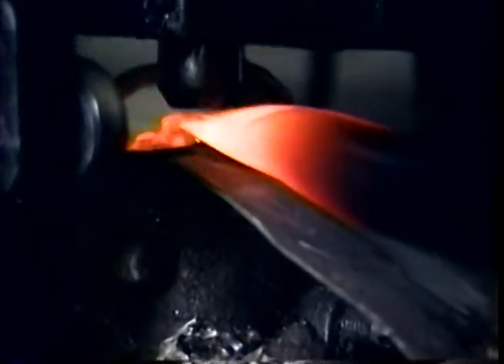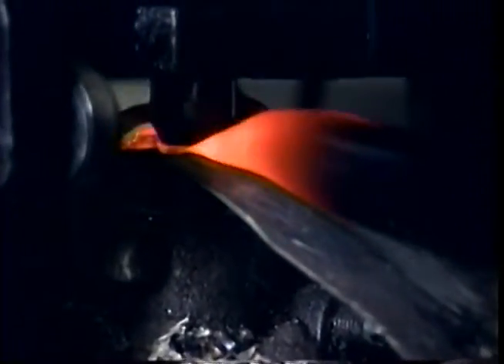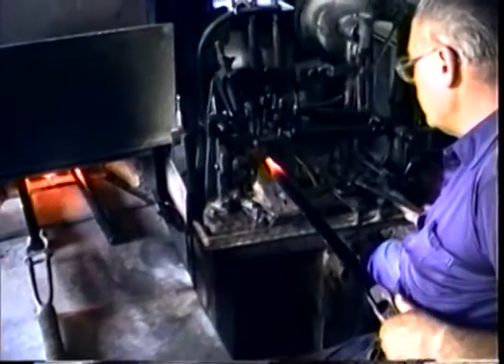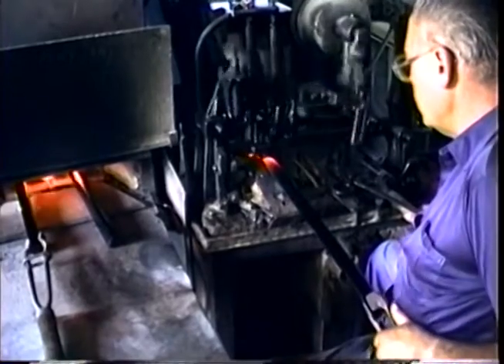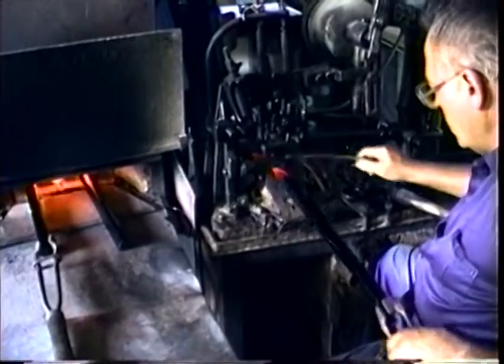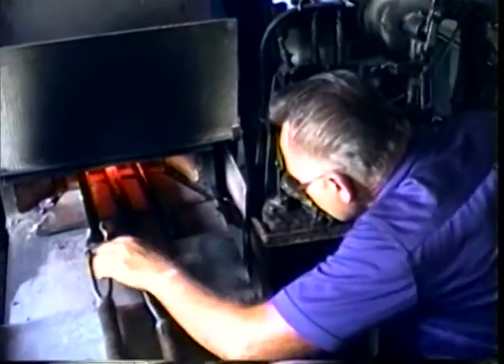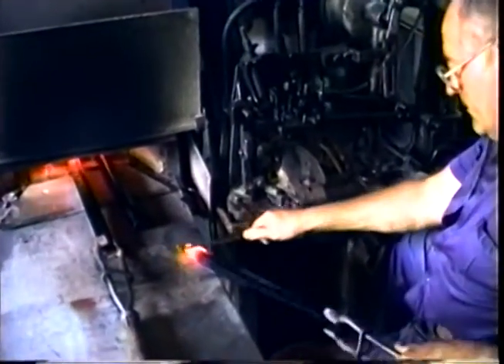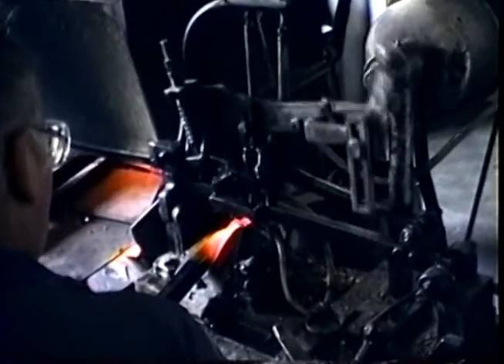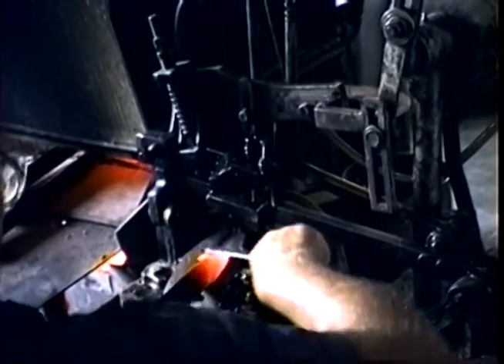He must time the movement of pushing the glass rod into the mold with the rhythm of the machine. They can get imperfections if the mold is not the correct temperature. This machine works a little differently than the others. Whoops, he messed that one up.